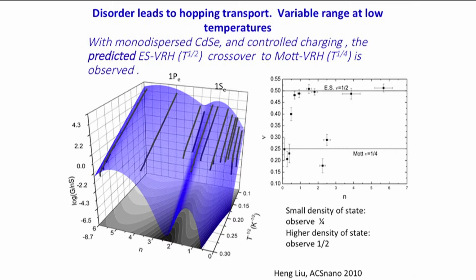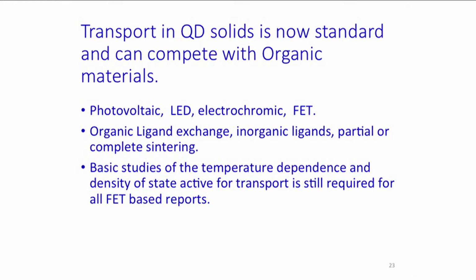And we showed that if you tune the density of states by picking the Fermi level across the dots, when you charge with a very small number of electrons, you're in the Mott regime. Then when you have of the order of 1 electron per dot, you're in the Shklovskii regime. And then with 2 electrons per dot, you're getting the minimum density of states, and so on and so forth.